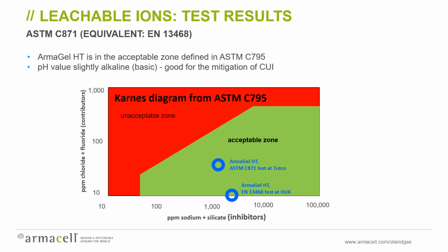We've also done a variety of testing for various corrosion processes and situations. So one of those was testing for leachable ions using ASTM C871 methodology. And the diagram that you've probably seen in a few documents before and was published in ASTM C795, the red zone on the left is where you do not want your results falling for parts per million of chloride and fluoride. The green zone is the acceptable zone.